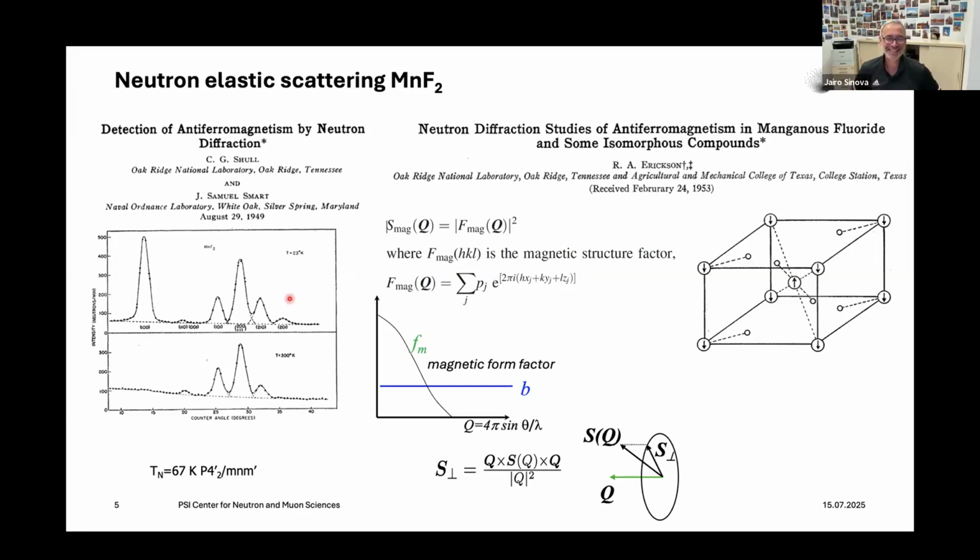It's quite costly. You pay by the size of the crystal, which should be larger, because when you do a polarized experiment, you're cutting intensity. You cannot polarize neutrons; you're just picking up from the beam those which are polarized correctly. So 3 times here, 3 times there. So it is 10 times less flux, and so your sample has to be large.